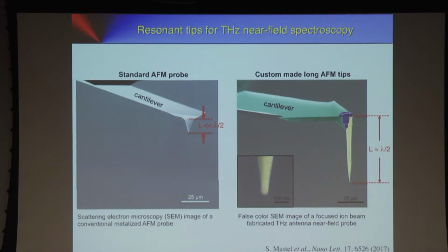So at the moment, we use standard tips. They are 10 micrometer long, we buy them, nothing is optimized. And as I said, the wavelength is huge in the terahertz, and then these tips are really much too short. So we adopt concepts from radio wave technology. We just make these rods, or these tips, as long as lambda over 2. In this case, we can expect a resonant excitation. So this works like a radio wave antenna, just now for terahertz waves, if we make this long enough.